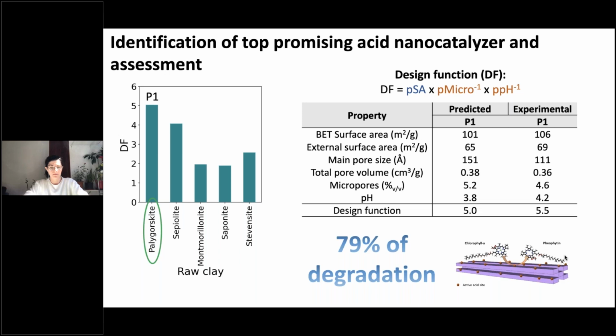79% of the degradation. A generally accepted mechanism involves replacing magnesium cations in the chlorophyll A structure with protons at the catalyst surface, and generally nanocatalysts achieve 65–75% of degradation. Our P1 prototype improves the performance, achieving 79% of degradation. Finally,